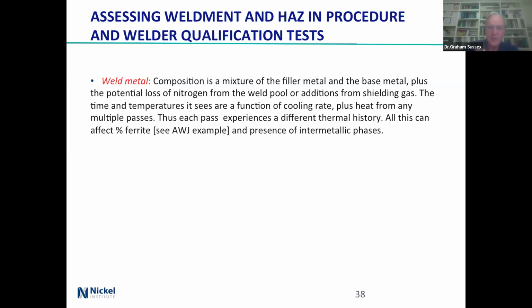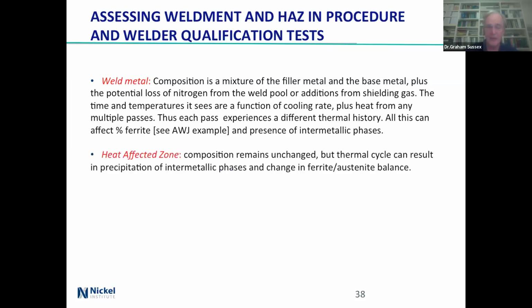Time and temperature is going to be a function of the cooling rate plus heat from any multiple passes. And I'll show you an example of that from the American Welding Journal. It's quite interesting. Each pass will get a different thermal history, and you'll get the percentage ferrite changing and different intermetallic phases. In the heat affected zone, the composition won't change all that much, but the thermal cycle means that you may get intermetallic phases and a bit of a change of the austenite ferrite as well.